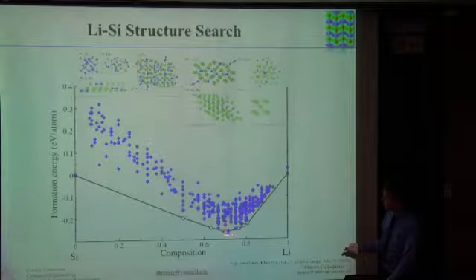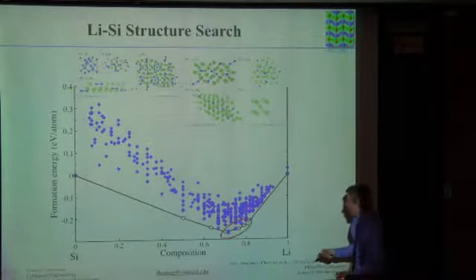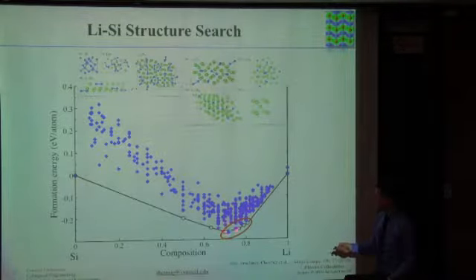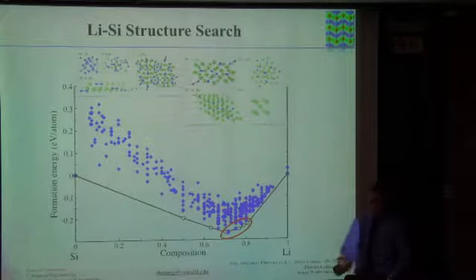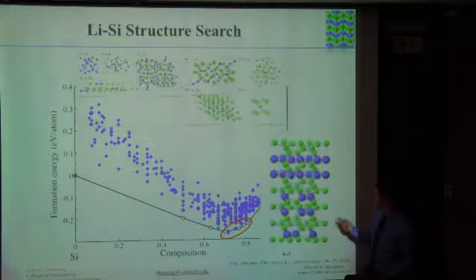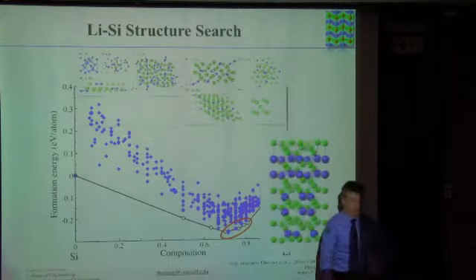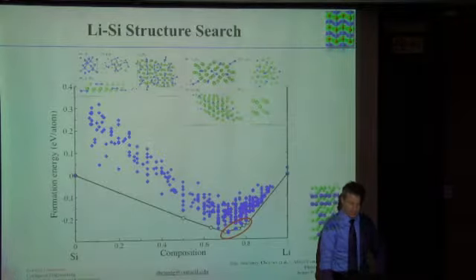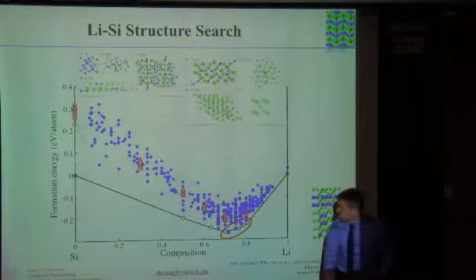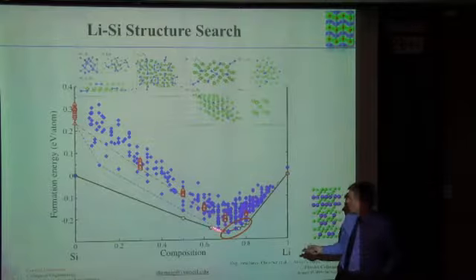Here's one which actually turns out to be lower than the convex hull, and a couple which are right on the convex hull. So we're going to focus on those a little bit. Here's the crystal structure. I'm going to show you later a little bit more about that. Let me just skip that for now. We also, so we draw in what the convex hulls for both those points is. And here's actually, we should have drawn the convex hull from here, going all the way down to here.